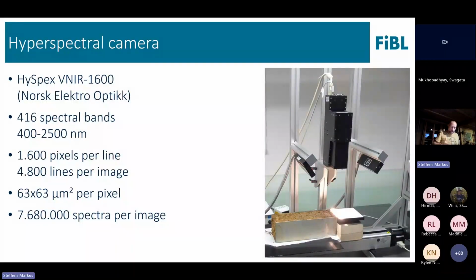So it takes a picture of a surface, and then you move the surface. Normally it's flying on a satellite or on a plane, and so it's flying across the surface. In this case, for calibration, it's put on the translation stage, so the sample is moving below the camera. And with this setting, so there is a lens inside, and each pixel has a spatial resolution of 63 by 63 square micrometers. So it's quite small pixels, so a good resolution.